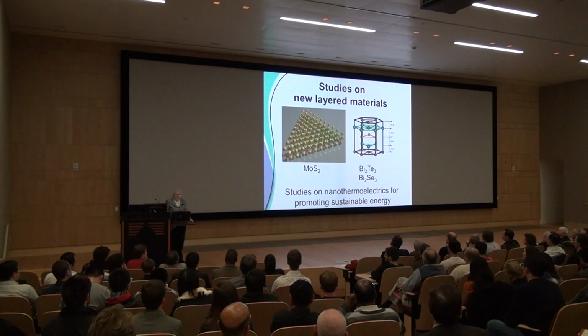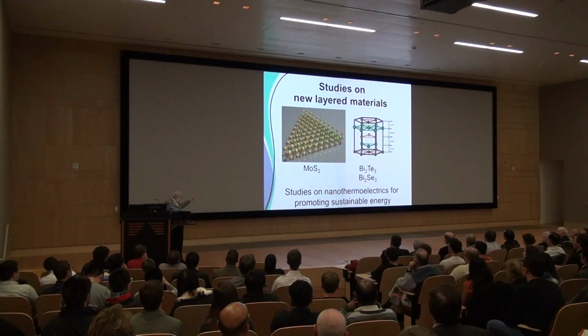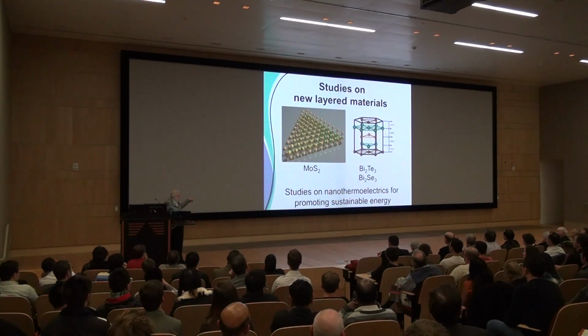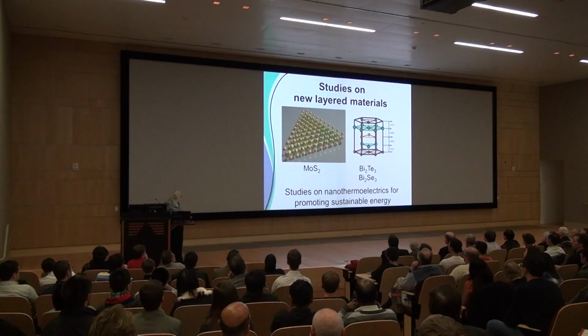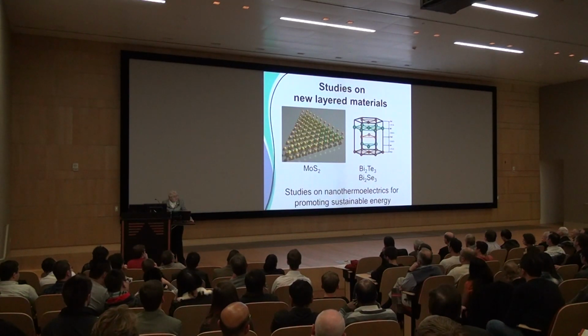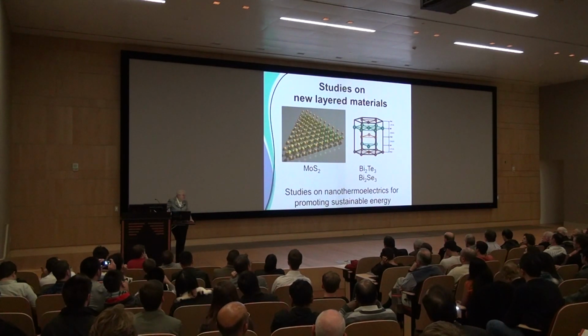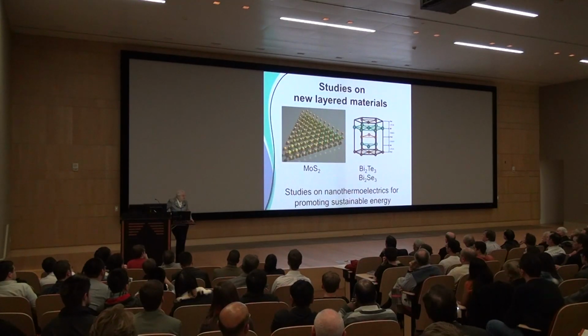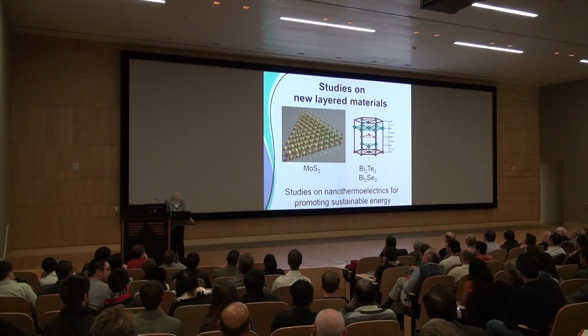So nowadays, instead of having single layers, we have cluster layers, as you can see. MoS2 is three layers, so two S layers, and then the Mo, moly layer in between. Moly disulfide and then moly diselenide, and there are a whole family of those things. And then the bismuth tellurides are even more complicated. They have five layers. But there's a whole family of transition metal dichalcogenides of different sorts that are interesting for these kinds of applications. Not too much work yet done on them. This could be an interesting area for something. We don't know exactly what the something is. The challenge of the unknown. So that's where I'm going to leave you.